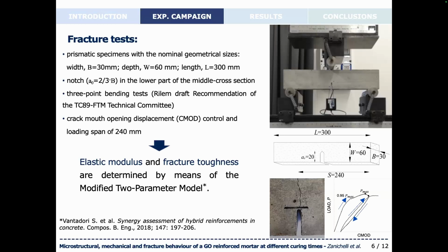As you can see in the graph on the bottom right part of the slide, which represents a typical load-crack mouth opening displacement graph according to the modified 2-parameter model, each specimen is monotonically loaded up to the peak load under crack mouth opening displacement control. Then, when it reaches a load value of about 95% of the peak load, the specimen is fully unloaded, and then it is finally reloaded again under crack mouth opening displacement control up to the final failure of the specimen itself.